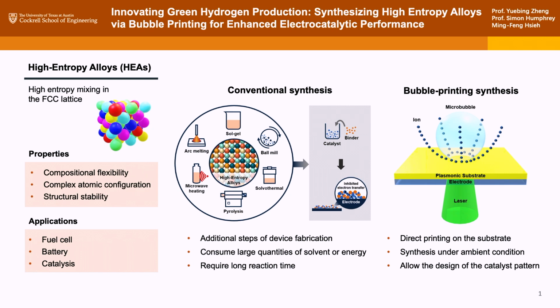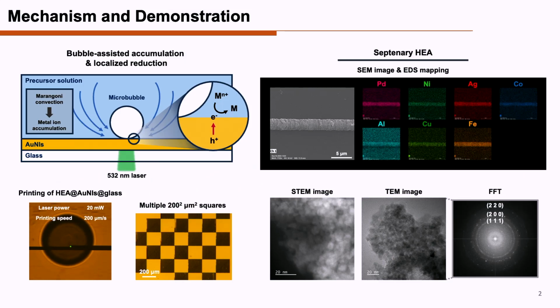We call it bubble printing synthesis. It's like a laser direct writing method. So we can directly print high entropy arrays on the substrate, which can be an electrode like FTO glass. And this synthesis is under ambient conditions. And also because it's a printing process, it allows the design of the catalyst pattern. So in this slide, I want to exhibit the mechanism and also some demonstration.